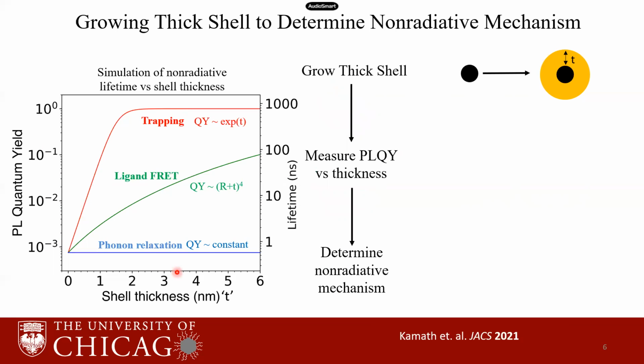So over here, we have an elegant method to determine the non-radiative mechanism. All we have to do is to grow a thick shell around the nanoparticle, measure the quantum yield as a function of shell thickness, and compare to these three models to determine the mechanism. Nobody has grown a thick shell around mid-infrared quantum dots before. So I first developed a synthesis strategy to grow the shell.